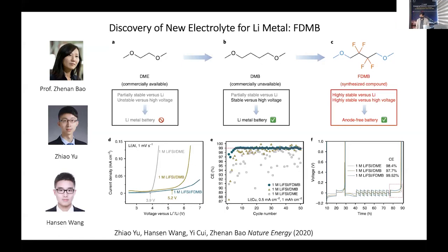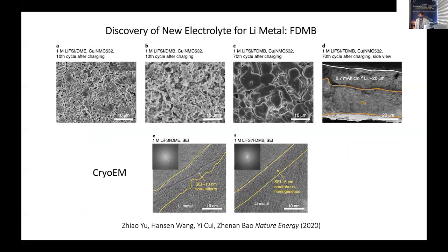So we looked into this further, and it built a very different morphology of lithium metal. If you look at C and D on the top, the SEM top view, it grows much bigger lithium metal grains. If you use other electrolytes, the lithium dendrites and filamentary lithium react with the electrolyte a lot. So the FDMB one is much better. And using cryo-EM, we can stabilize the SEI, the solid electrolyte interface, and we also find that it's more uniform.